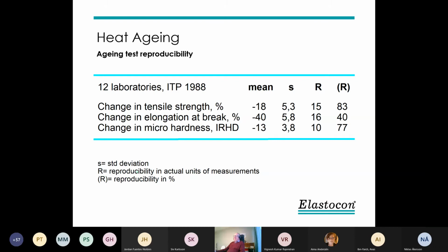but the big R, which is the reproducibility in actual units of measurement, that is percent in this case, is almost as large as the mean change. And the R in parentheses is the percent of R calculated on the mean change. So it's quite high.